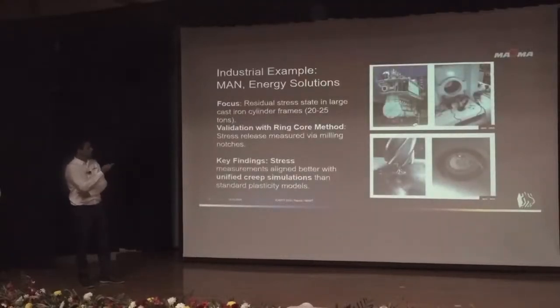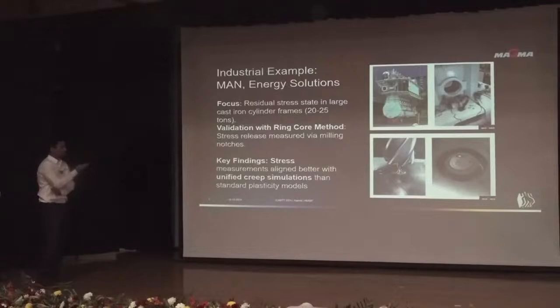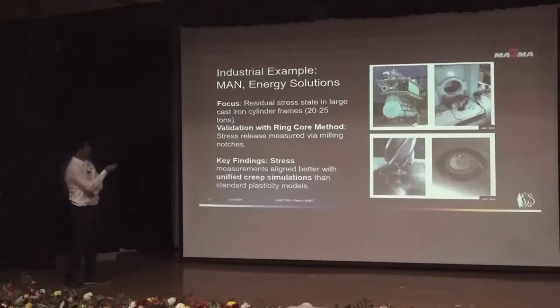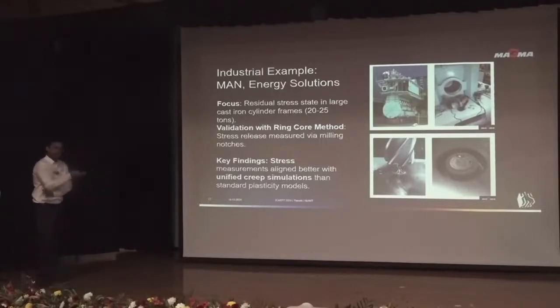So here is a case study of a MAN Energy Solutions casting, where the focus is on residual stress state prediction in a cast iron cylinder. We are going to validate a ring core method for that by doing milling and creating notches and releasing the stresses, and also simulating them with the software. So what are the key findings? Stress measurements will align better with the unified creep model.